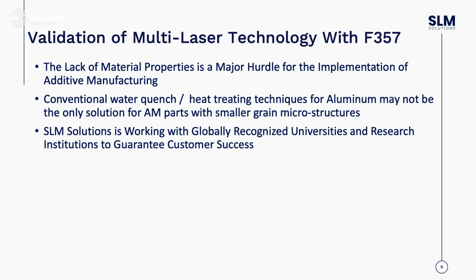So what we wanted to learn in using your technology is whether we could achieve the mechanical properties we were looking for by quenching quickly enough to suppress the formation of the precipitates in F357 and then age them to get the optimal yield strength. This is the typical process for a T6 temper in these types of alloys. If you're not able to cool quick enough, you get enough precipitation and growth of the precipitates during the cooling process that you've already passed the peak strength of the alloy before you have a chance to properly develop the precipitation during age. So a fairly rapid quench in these types of alloys is critical to getting the mechanical properties.